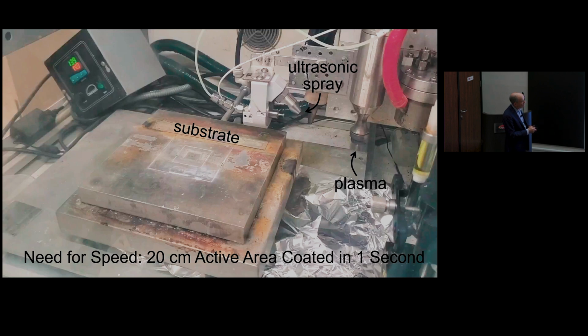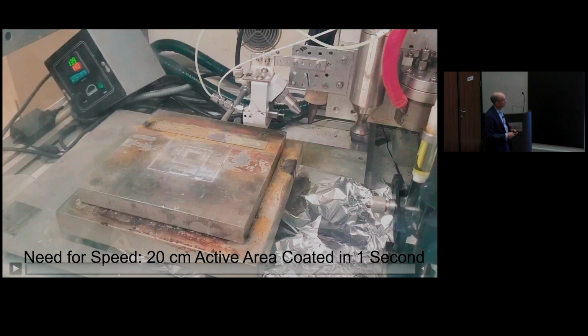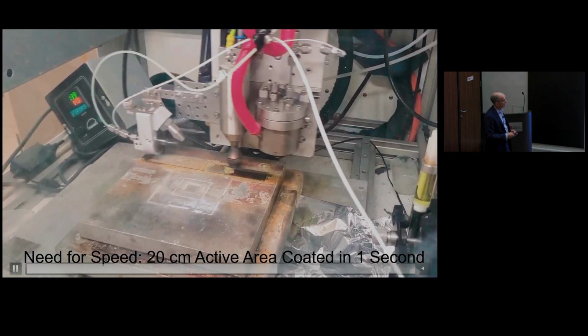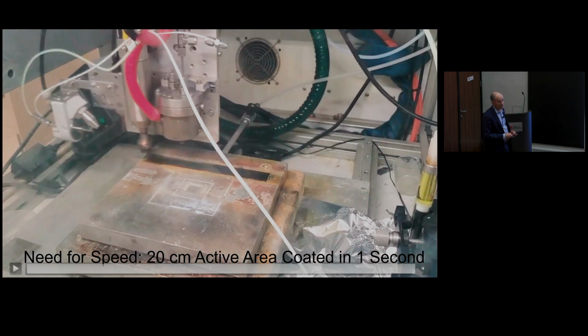And so what you'll see is that this is going to come down, deposit the precursor solution, which you won't see because it's transparent. And then the plasma will come along, and you'll see in real time both the deposition and the full curing of the plasma. So no subsequent processing is needed. And that's it. That's produced the perovskite in that one single pass. So we have no restrictions on this length here. We have another system where we can go over longer distances, but you can see that it can be done very, very quickly.